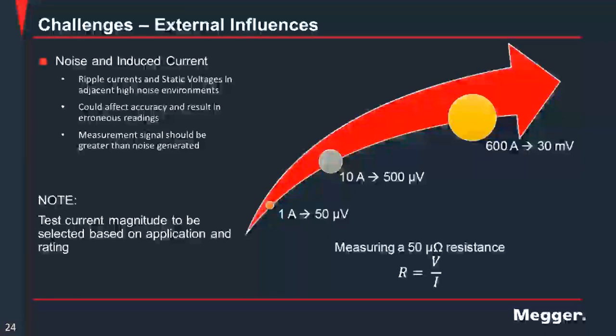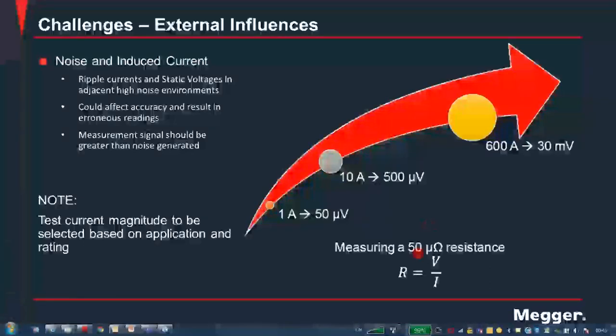You can see it on the right screen here. For example, measuring a resistance of 50 micro ohm. If you test with 1A, you will get a voltage drop of about 50 microvolt to get the 50 micro ohm. When you test with 10A, the voltage drop will be measured about maybe 500 microvolt. So which one is the best depends on the background noise that you have on the site. If you have background noise of maybe 100 microvolt, the 1A measurement with this voltage drop will have an effect on the measurement, because the background noise is higher than the voltage drop measurement. We need to avoid this condition.